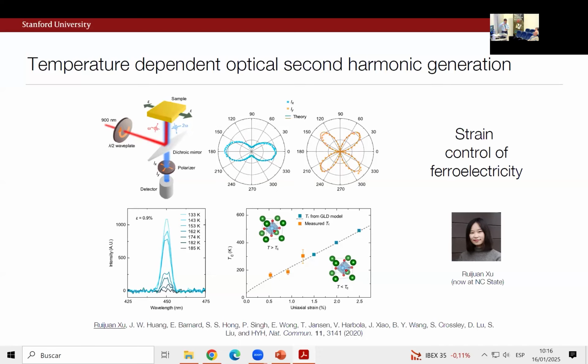But what was convenient for us is whereas we could only do PFM, at least within our group, at room temperature, this gave us a way to chase the onset of ferroelectric order along this channel. And it's quite dramatic, actually, right? So you can see here, these are the samples or the ranges that we could access with these sorts of experiments. Let me be clear and say this is theory. These are results of a model extrapolating out. And by something like 2.5% strain, we're inferring TCs of on the scale of 500 Kelvin, right? So again, a pretty exciting opportunity to use strain to access in one sample multiple phases.